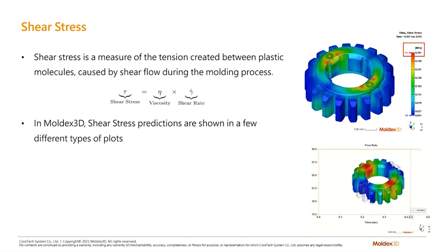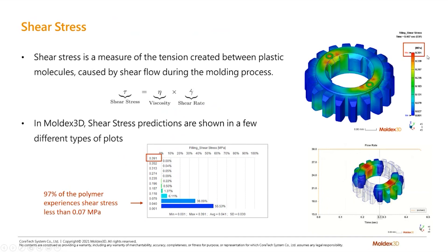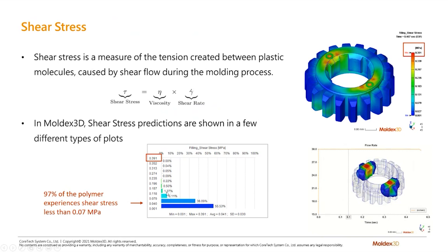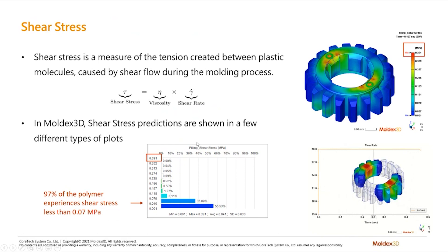This is a snapshot in time at end of fill — it won't show you where higher shear stress occurred during fill. There's another plot that gives us the actual peak values. Looking at this particular part, you can see the max shear stress is 0.39 megapascals. In the center chart, which shows a different way to look at results, we can slice the part and see that actually 97% of the polymer is occurring at very low shear rates — actually below 0.07 megapascals. So although we're seeing red areas, we can look at the data and quickly understand whether that could be impactful to our project.